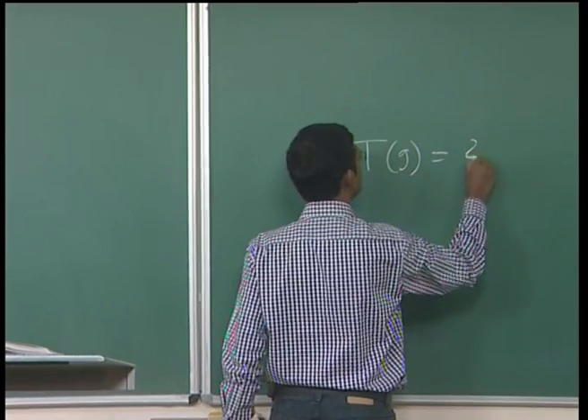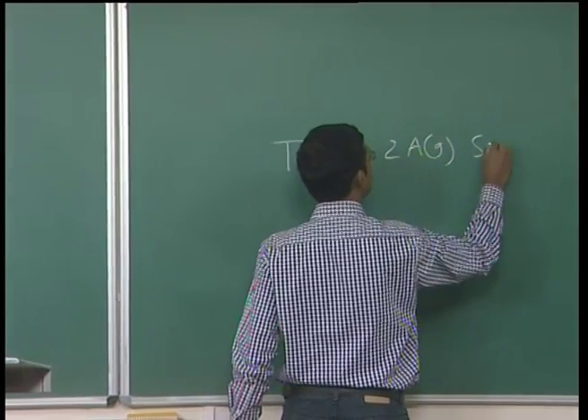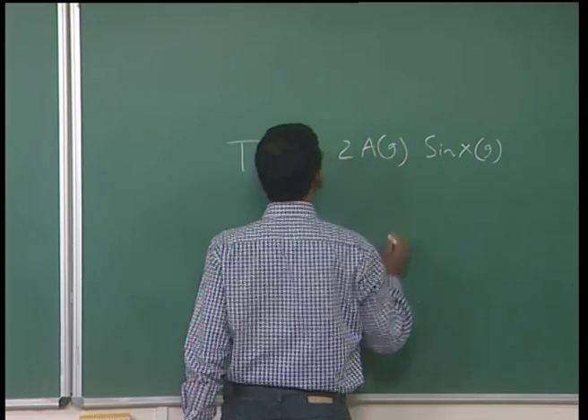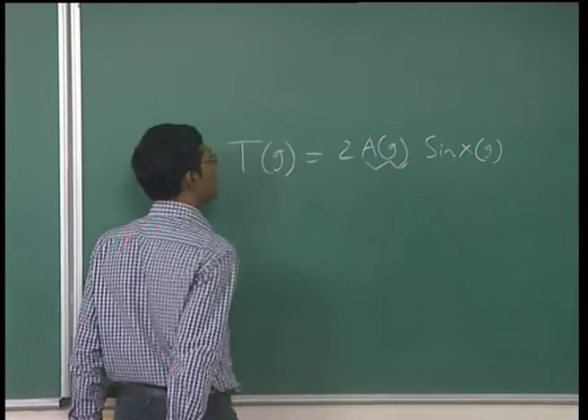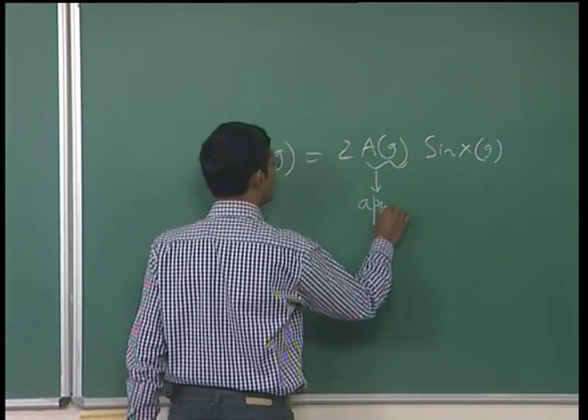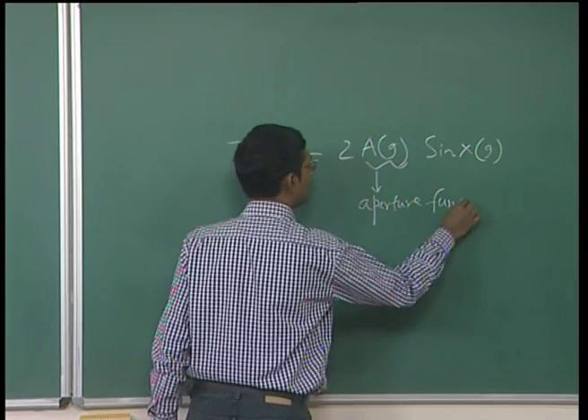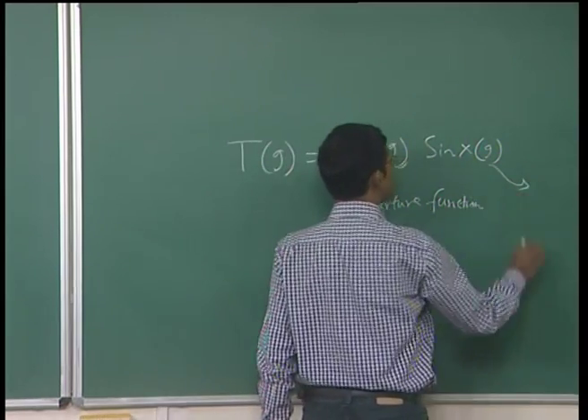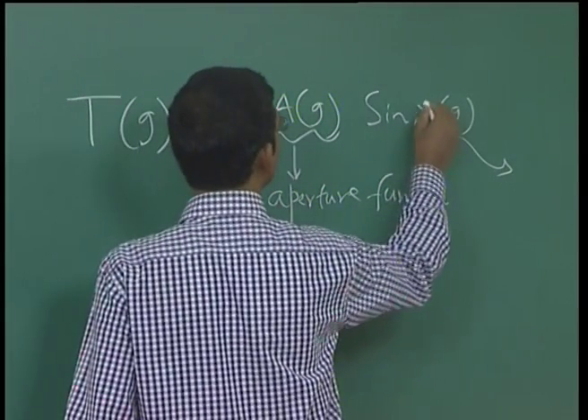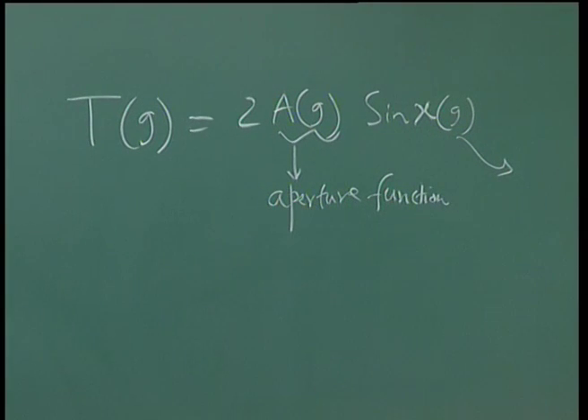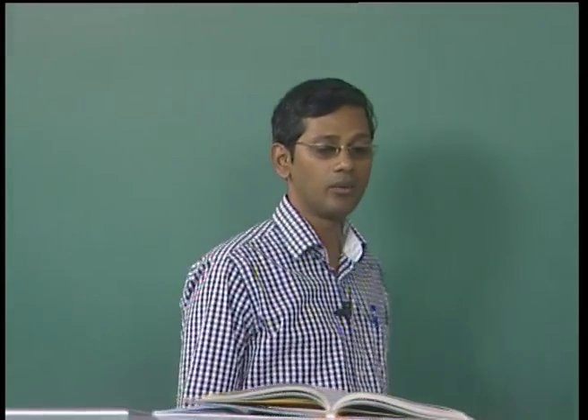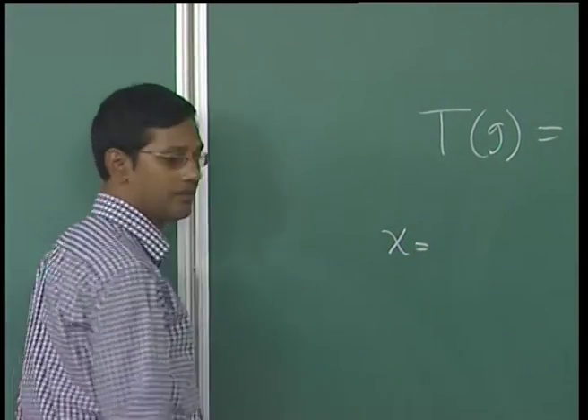Transfer function is equal to 2, where the first factor, as a function of g, is basically the aperture function, and this actually is a strong function of g and chi. Chi is basically the angular factor which comes into play. From this function we have seen how chi plays a very important role, and finally we derive the optimum values of chi. The one which I can write like this depends on